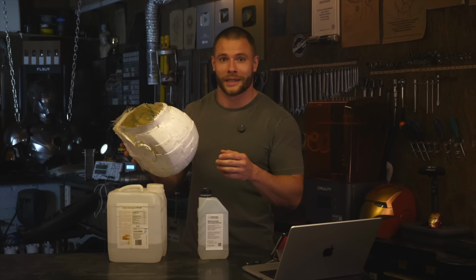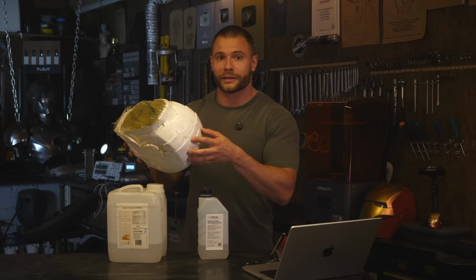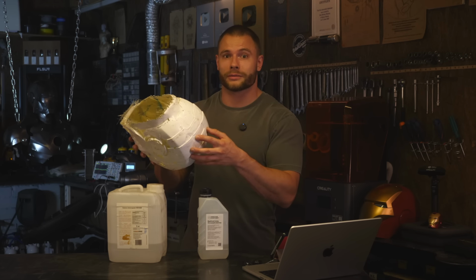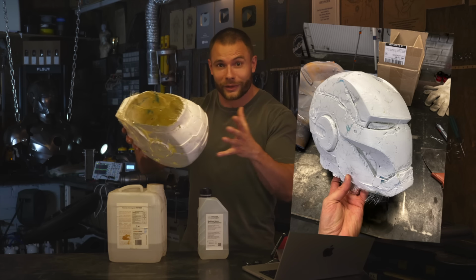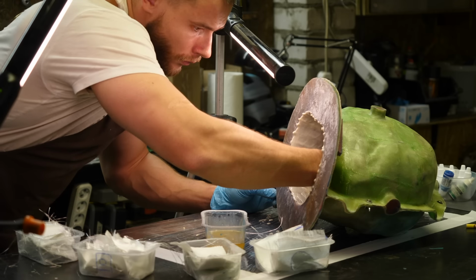I'm really amazed by polyester's ability to sting so hard even through the glass. And I would have been ready to do casting in an open field, but the problem is also that polyester gel coat turned out to have very weak adhesion to the silicone mold, which again was not an option. In short, I hit a wall. I couldn't reinforce the casting with composite, meaning I couldn't do the very thing all this work was about.